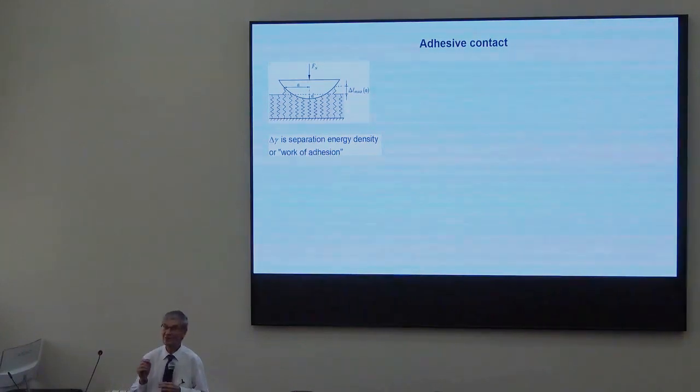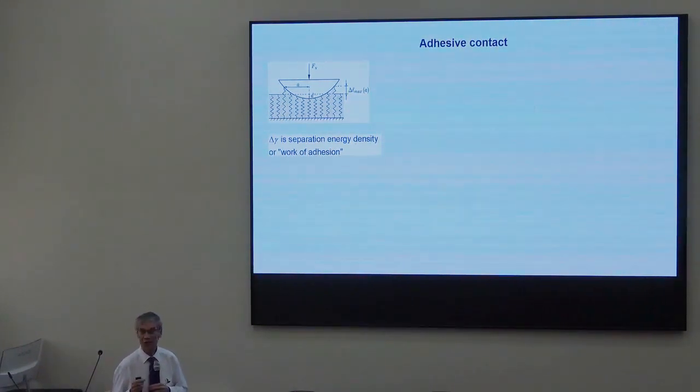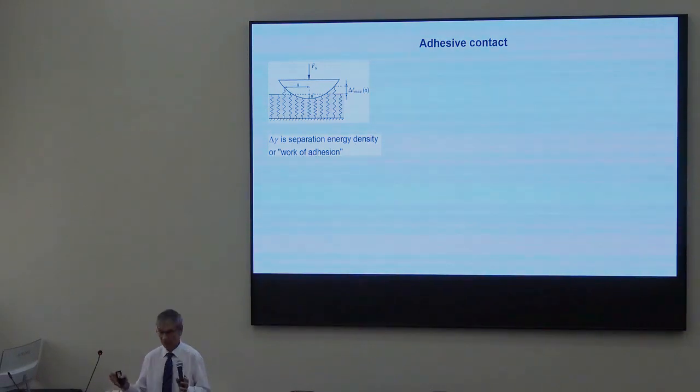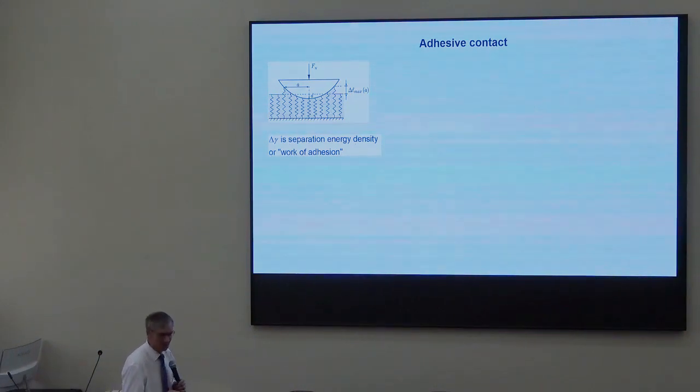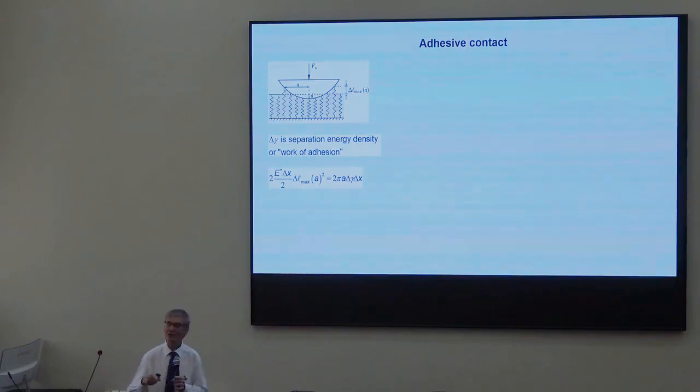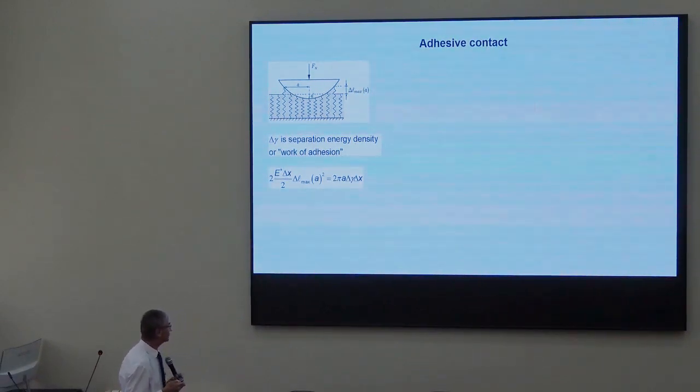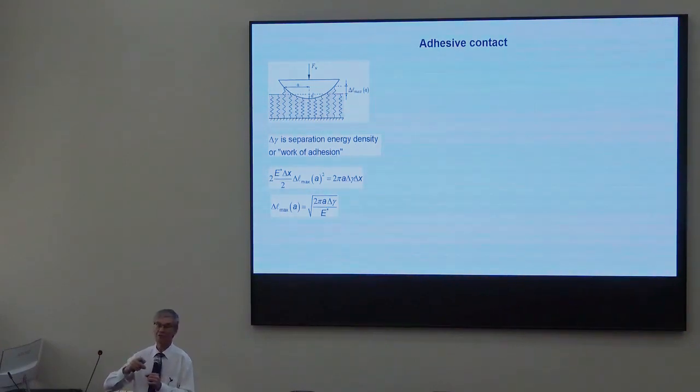And the same idea is very simple to implement in the framework of the MDR. If the boundary is displaced by delta x, the distance between two adjacent springs, then two springs are released, from the left-hand side and right side, and the energy released, the energy stored in one spring, is of course very easy to calculate. We relate it to the work of adhesion of the ring-shaped area that appeared due to opening, and get the criterion for the detachment of the boundary springs.